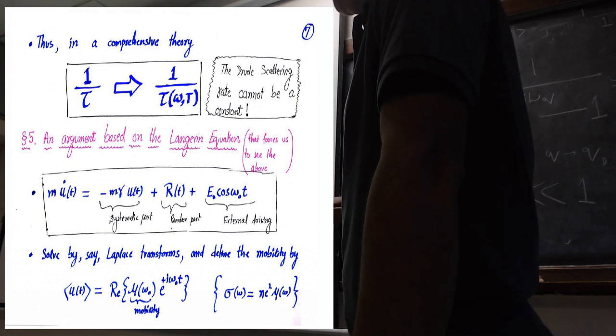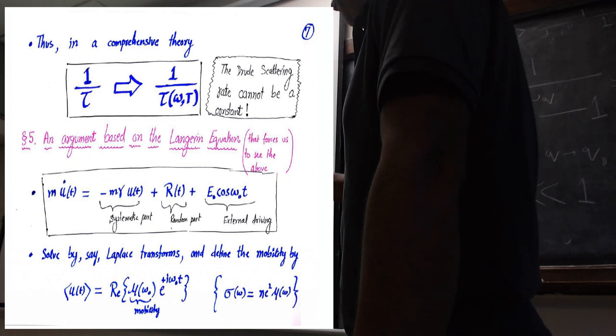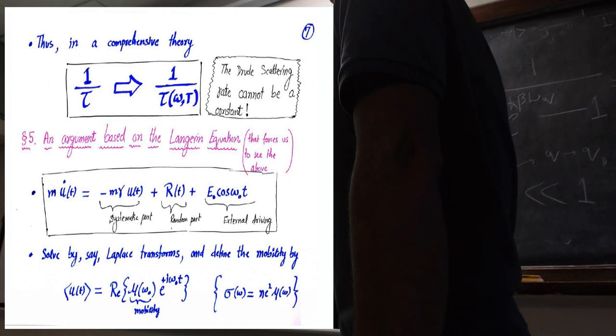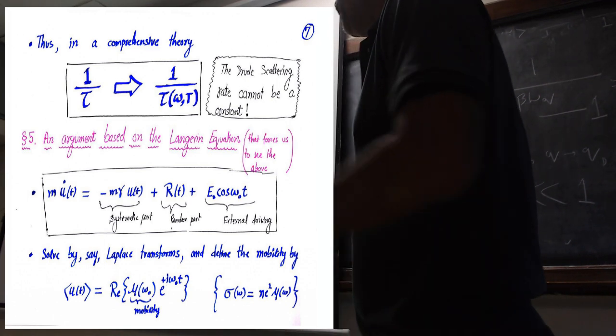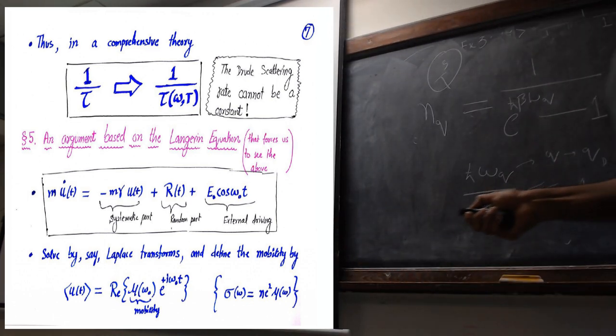Now the thing is that in this simple looking Drude law here, this tau seems to be a completely constant factor, but it turns out that this is not a constant actually. This actually depends upon frequency and temperature. This is called the generalized Drude scattering law. So how do you go from this 1 by tau to 1 by tau(ω, T)? That's a very beautiful chapter in non-equilibrium statistical mechanics.